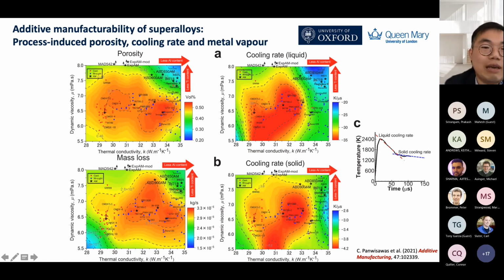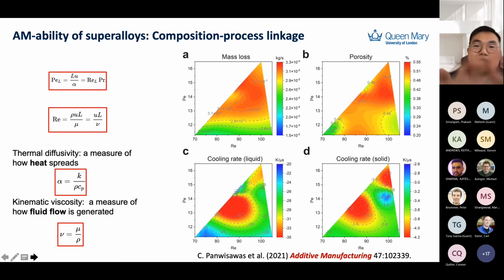And this is because if we understand this interaction and then we summarize the map for superalloy here, you will see that there's some hotspot from the thermal fluid point of view where you can get some kind of processing window that avoids a lot of mass loss or gets a quite optimum cooling rate. And I have to note that this is at a condition investigated. So we need to use this information to optimize further for a particular material and process, also machine as well for additive manufacturing.